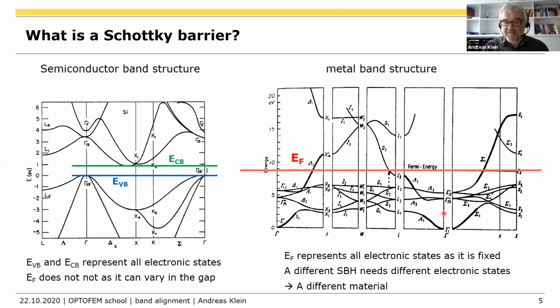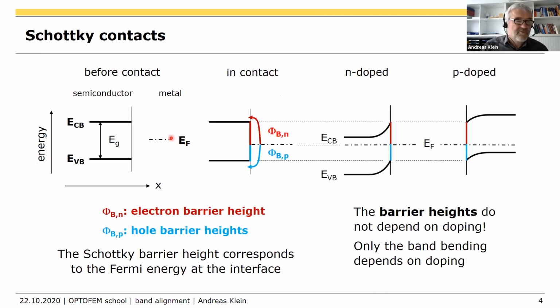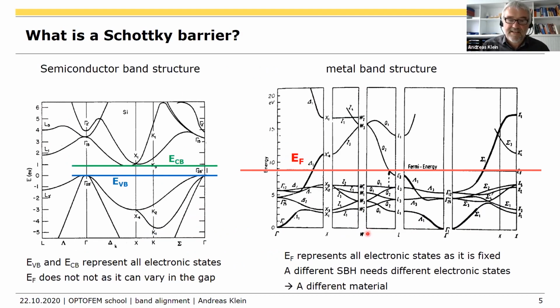Now that's the band structure of a metal. That's copper, because you see here the s band and you see here the flat d bands of the copper. And the Fermi energy is here. The Fermi energy is fixed because it's given by the number of electrons. Each copper gives 1 electron into the s band and 10 electrons into the d bands. That means the occupation of the states is really fixed. So this Fermi level, this line we show here, is just a representation of all electronic states in the copper.